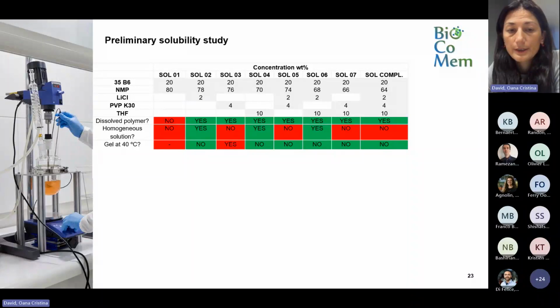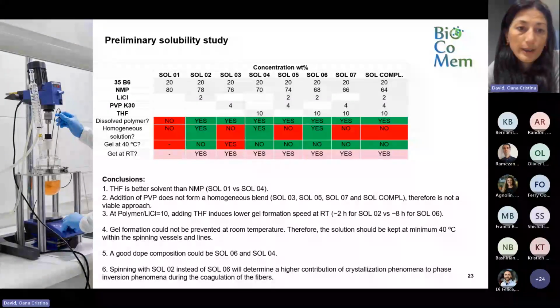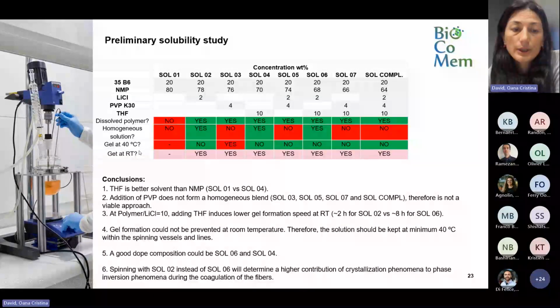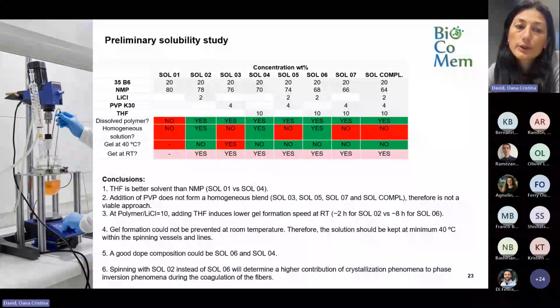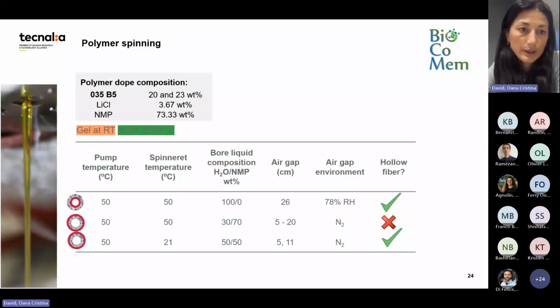We also observed that these solutions are liquid at 40 degrees, but at room temperature, they make a gel. So based on this, we realized that we need to do spinning at 40 or higher temperatures. So we did a few spinning experiments with this lab scale batch. And with these first results, we realized that we can make hollow fibers, and we can make the selective layer either inside or outside.